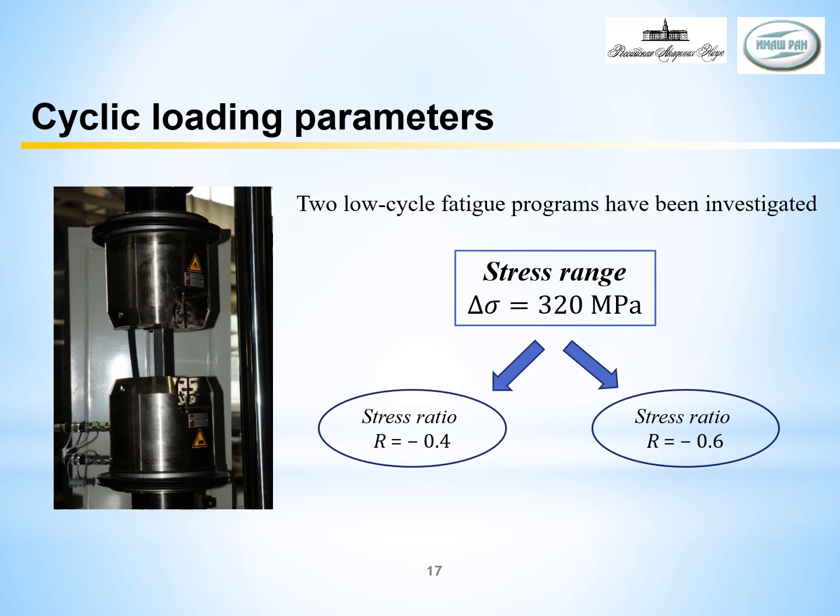Two low cycle fatigue programs have been investigated. The stress range is a constant value and equals 320 megapascal. The stress ratio was minus 0.4 and minus 0.6.